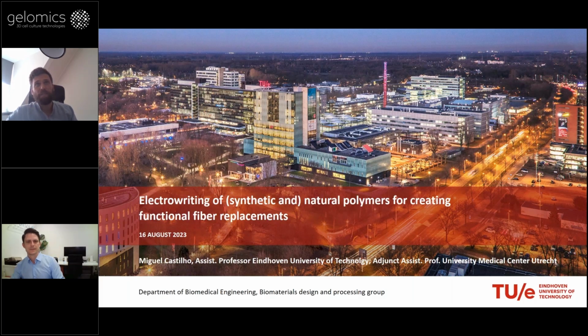Well, keep in mind that in electrowriting we are basically combining two forces. So the electrical force with either the pneumatic force or the mechanical force that you might use to dispense your material. These will lead to shear forces inside of your nozzle. One has a contribution of two forces here, while in extrusion-based printing it is basically just due to the pneumatic pressure or the mechanical system that you are dispensing your material with. I think the shear thinning, you are referring to the material properties that you achieve, right? And how is that different between one and the other?